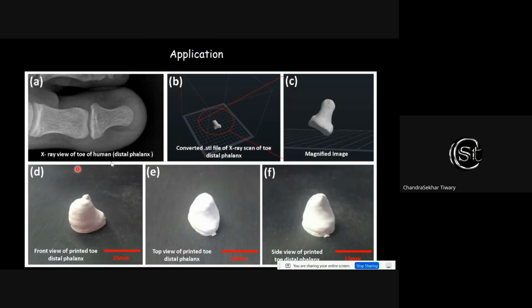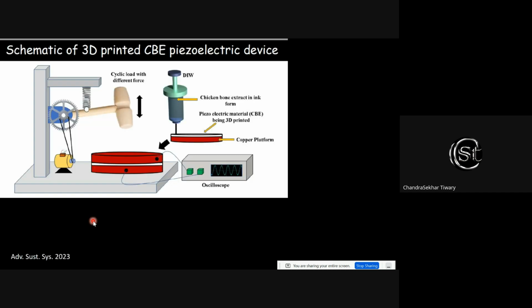We have shown here as a demonstration in the work that kids' bone is very difficult to replace, because depending on age and their background, this can change. So there is no right dimension for the bone of the kids. So what we did, we took the real broken piece, scanned it, and then 3D printed the structure. Now, because of the fine particles, the surface roughness and the dimensional tolerance match exactly with the real structure. As a result, it can be easily replaced. And again, it's a green method. We don't put any harmful additives. So hence, it can be directly implanted into the living.